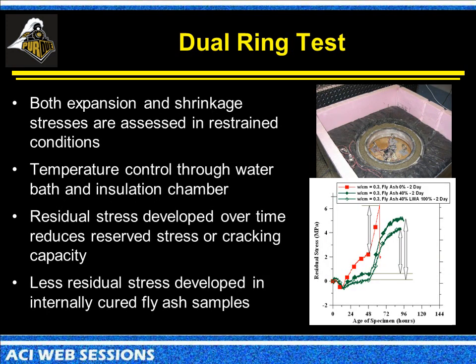So in addition to keeping those temperatures lower, what we really wanted to do is we developed something called a dual ring test. And the idea here is instead of just having a single ring, we place this concrete in between two rings, and we have the ability to change the temperature of this concrete as a function of time. So we'll place this in here. We'll actually have a water bath that controls the temperature of these rings. The rings are actually made out of a special steel that doesn't allow it to move, so the restraint doesn't change as the temperature changes.